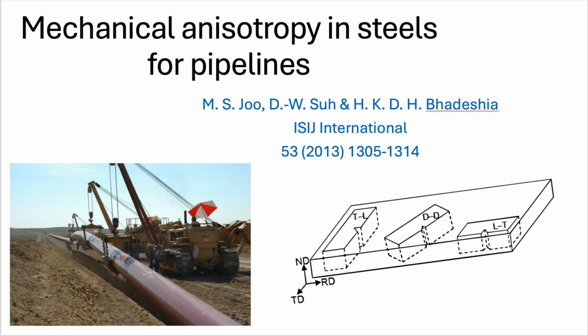Does texture become more important as you go to stronger steels, like moving from X65 to X80? Generally, yes. That seems to be the trend. In older or lower grade steels, the inclusions and the banding are often such big problems that they dominate the anisotropy. The low-hanging fruit, so to speak. Right. But as steelmaking gets cleaner and processing more controlled for grades like X80, you reduce the impact of inclusions and banding. Then the underlying crystallographic texture can emerge as the main factor controlling anisotropy. It becomes a limiting weakness. It's like peeling an onion, solve one layer of problems and reveal another underneath.